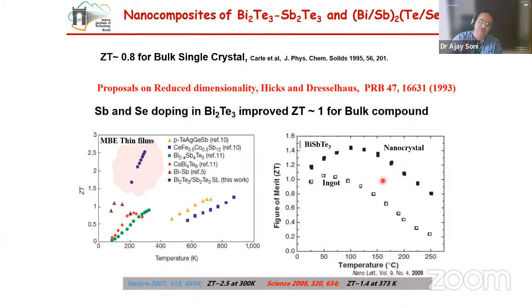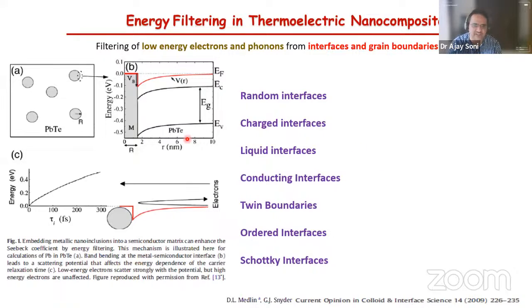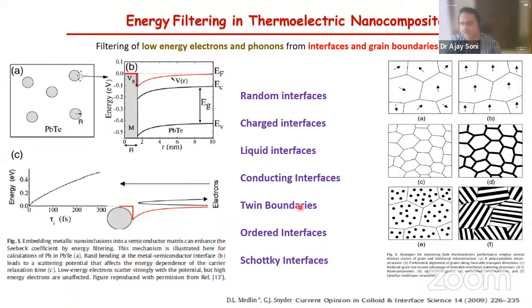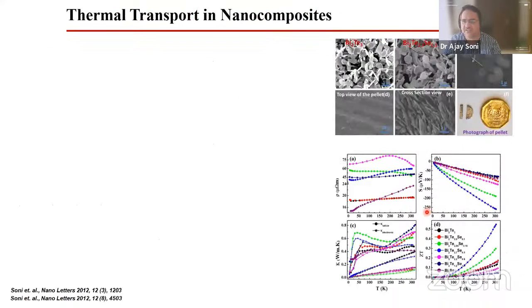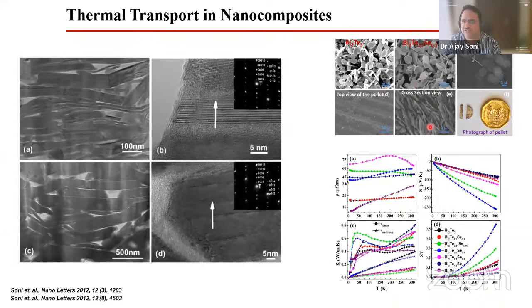So the idea was actually to create more phonon scattering centers, or create some interfaces. What they do is, at these interfaces, the low energy electrons will not transport the heat or the electricity, but the high energy electrons will do that. And that way you can control some of the charge carriers in these narrow band gap materials, and then one can design different kinds of strategies in the nanocomposite. This is one of the things which we also did about 10 years ago or so, and we could utilize the interfaces to get more scattering centers.